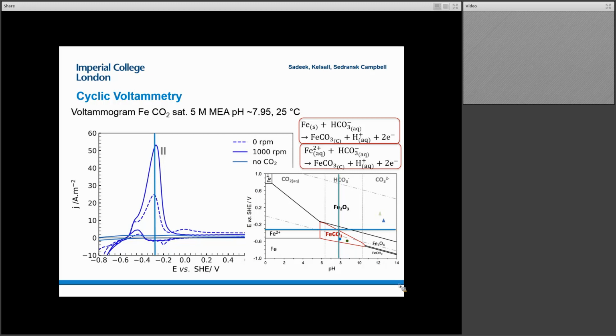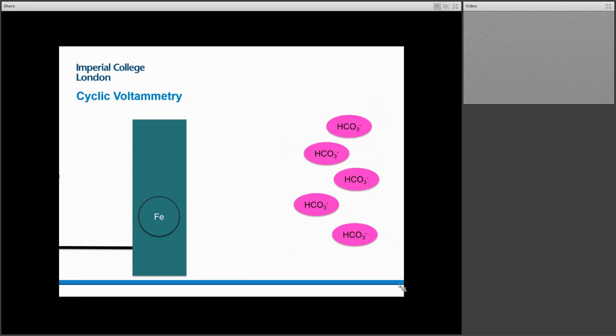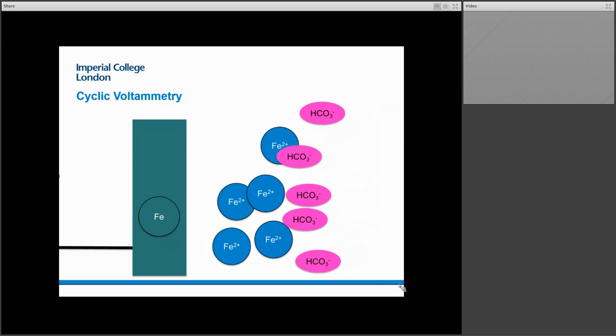And one of the things by introducing such variables as rotation, scan rate, temperature, is we're able to elucidate more about which mechanism it might be. And so in this instance, I am going to gloss over it a bit, but we are able to understand that, due to the rotation in particular being one of the factors, we are likely observing a reaction which is solution-based. And so this is also contributing to a wide range of research going on, trying to understand these kinds of phenomena about reactions being surface versus solution-based. So if we go from there, because I'm sure you can already see that there's other peaks of interest. So we have this initial reaction where we're forming our oxidation.